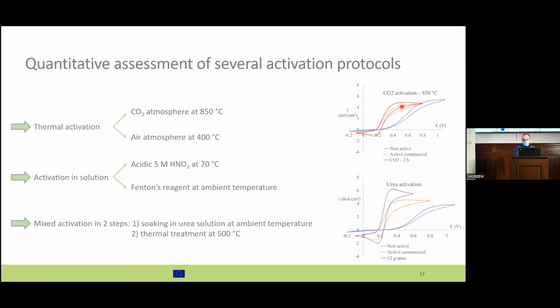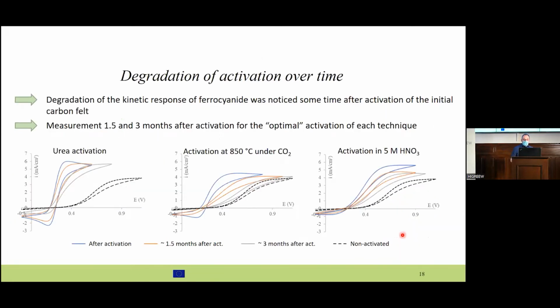So we have the non-activated material. When it is on the right, it is low reactivity. And when we do the activation for a certain time, we move this electrochemical reaction to a lower potential, and we increase the kinetic. And the same here for another example. And with the best activation we tested, we reach an activity that is higher than observed on the commercial activation. So this is one result of HIGREEW.